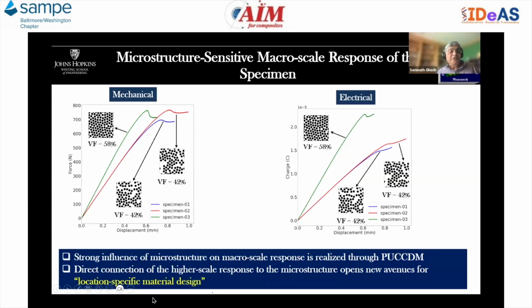Just to show the strong influence of the microstructure on the macro scale response, it is realized through these PUCCDM simulations. What you see here is the force displacement behavior corresponding to different microstructural representative volume elements. You see the volume fraction affects both the elastic and the damage behavior, but for the same microstructural volume fraction, just having different distributions affects the overall damage response.